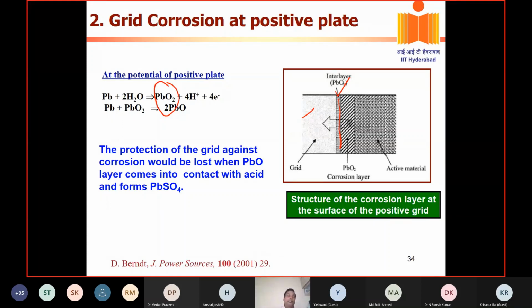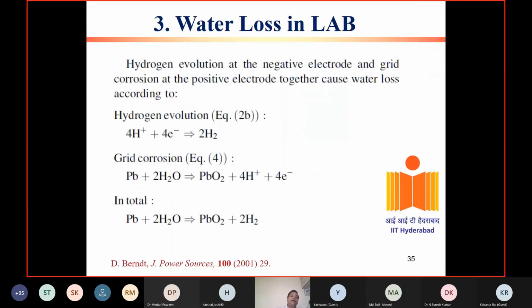Then the current may not pass, and then you may have joule heating and other issues. We'll talk about them. So part one is the low utilization of active material. Second one is grid corrosion. Third one is that hydrogen evolution and grid corrosion can together cause water loss. Even hydrogen evolution and grid corrosion, what I talked about in the last slide, can together cause water loss. You can have water loss because of these two reactions.